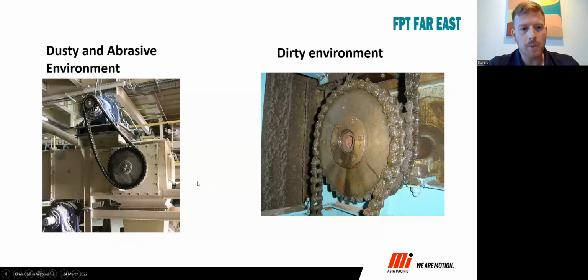So again, just to highlight some other areas you might have seen. On the left-hand side, dusty and abrasive environment. This is a cement mill. There is lime and clinker and all sorts of abrasive dust that's in the environment that lands on the chain. So it needs to work and operate in that. A dirty environment on the right-hand side. This is, from what I remember, a painting line where they paint cans, and it's very much over lubricated, but for a good reason. So a lot of the dirt is clinging to the outside and not going into the working components. So quite interesting demanding applications for chains.